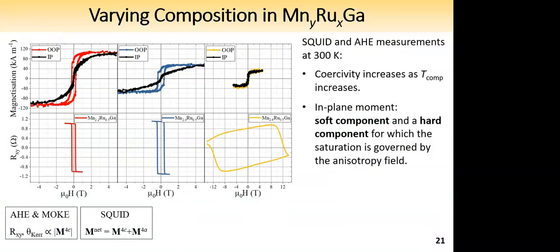First, I am showing SQUID loops in the top panel for 3 different manganese compositions within the ruthenium 0.5 series. On the bottom, we have the anomalous Hall effect. I'm again reminding you that in anomalous Hall, the resistance is proportional to the 4C sublattice, and in SQUID, we have the net moment, which is the sum of the 2 sublattice magnetizations. So let's look at the hysteresis loops taken at 300 Kelvin. The magnetization in SQUID is equal to the net moment. And what we see is that the coercivities between the anomalous Hall and the SQUID basically match.